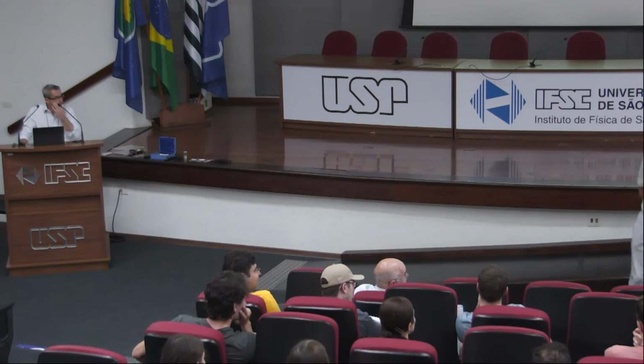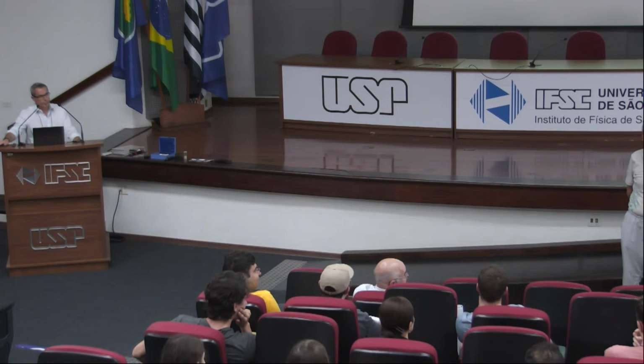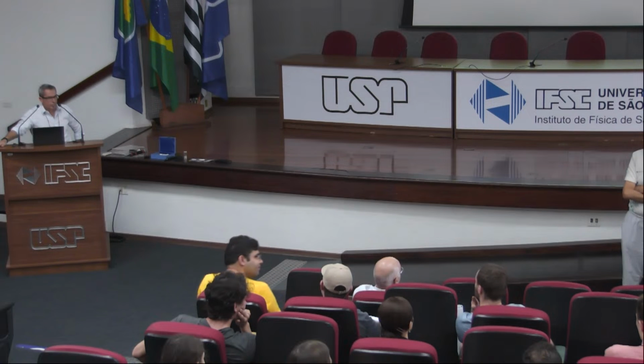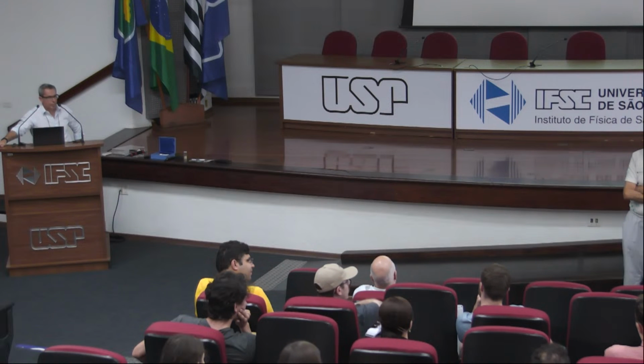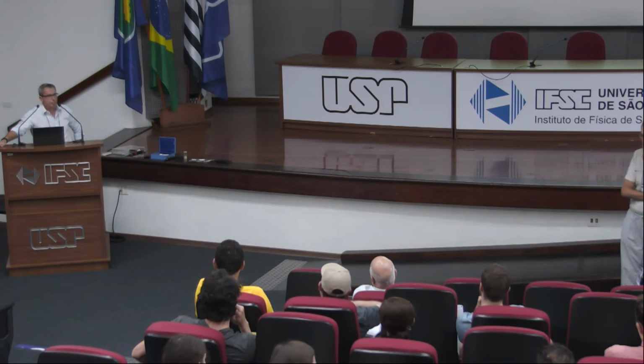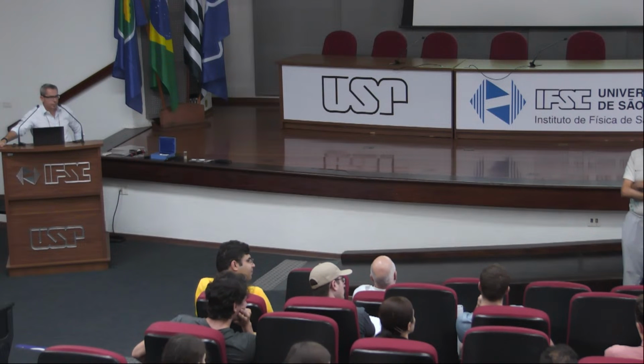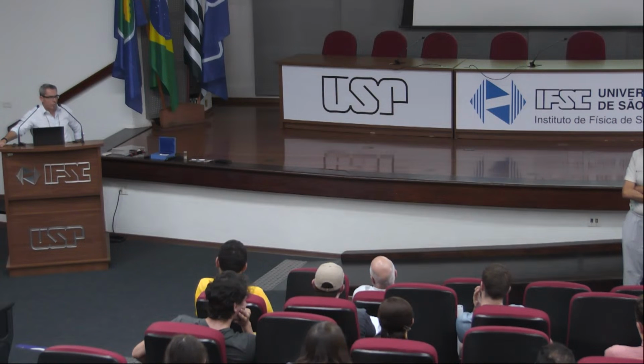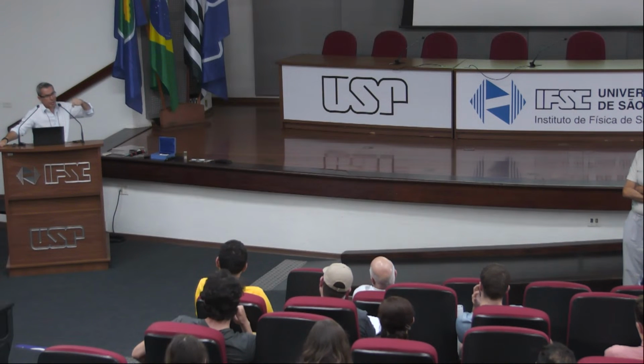I'm Anthony Secrekas from Lehigh University, and my question is related to the femtosecond laser irradiation you're doing to create your silver nanocrystals. Were you doing a heat treatment following the laser irradiation to grow the nanocrystals, or were they grown from the laser? From the laser. Yep. And then how well were you able to control the size of the nanocrystals with the laser? By controlling the power of the laser. And of course, it depends on the speed that you are writing, okay?